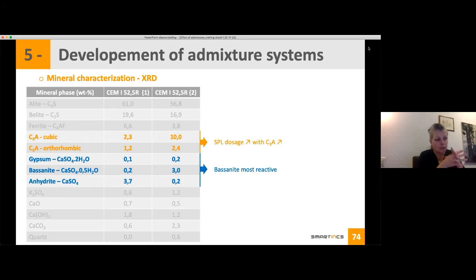So what is complex in assessing the situation is that you don't always have one parameter that changes at a time. You have at the same time the C3A and the distribution of your sulfate changing. But if you have more aluminate, then you can say, okay, I will have an increase in my superplasticizer dosage. If you also look at the type of sulfate, your bassanite will be the most reactive. So it will also increase your superplasticizer demand, because it will react really fast with your C3A, forming ettringite really fast, and the ettringite is also surface area to adsorb your superplasticizer.